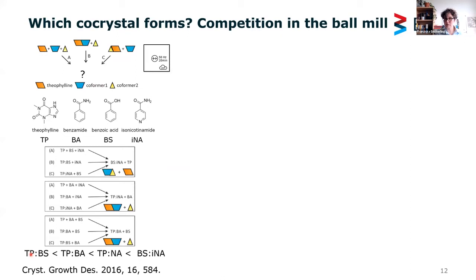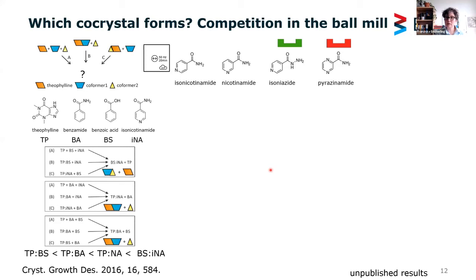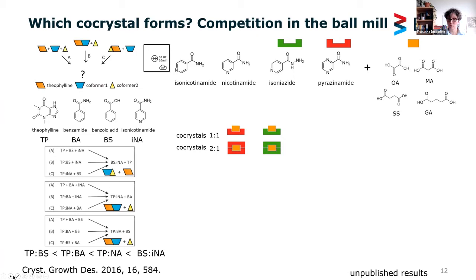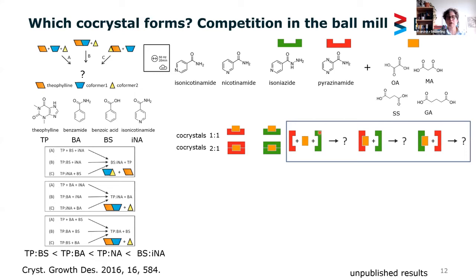So this was an older study, but also in a recent study, we compared the situation for pyrazinamide. We also used pyrazinamide with different other, very similar molecules, so that there will not be any steric issues. And you can see here isoniazid, which is especially of interest because this compound is very similar to pyrazinamide, and we were wondering whether we can get a ternary co-crystal with those two. And we used as co-formers in this case different dicarboxylic acids, and again, the same type of reactions. So we were looking for either 1-to-1 or 2-to-1 co-crystals, and we would challenge them. React all three compounds, or we would challenge an existing co-crystal with another one.